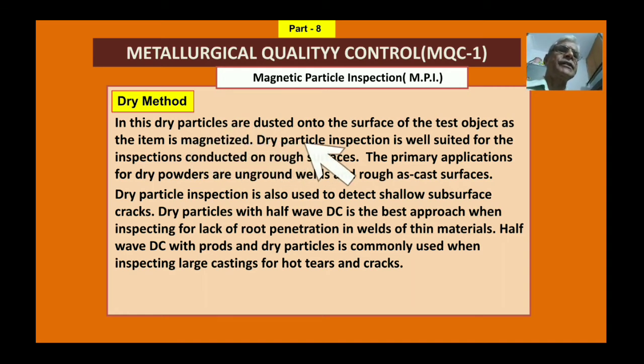So this way, dry particle inspection is well suited for inspection conducted on rough surfaces. The primary application of dry powder is on unground welds and rough as-cast surfaces. This dry method is generally used for heavy castings, rough surfaces, and welding. Heavy weldments you cannot put on the fixed machine because of their weight. So in this case you have to use the prod technique or movable technique, and there you use this dry powder either in black or red color, and then you can see the crack.